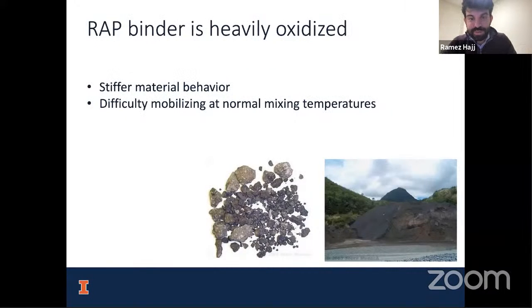So the vast majority of designs just say, get 30% RAP or get 40% RAP and mix this into your asphalt. This is not going to work well because if it's not compatible with the virgin asphalt, the RAP essentially is just acting like a rock. And if it's too stiff, it's just acting like a rock, which means that you'll have an inadequate binder content, and these aggregates will strip or crack immediately. You'll have loose aggregate at the surface.